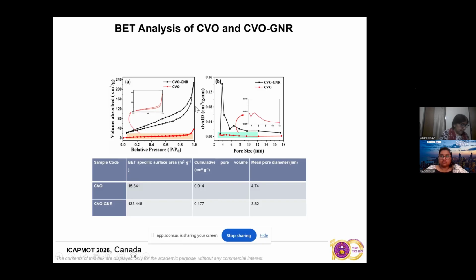It displays a combination of type 3 and type 4 isotherms, suggesting that adding GNRs introduces mesoporosity while still allowing multi-layer adsorption. So the introduction of GNR enhances the... you can see that then we have this pore size distribution curve.